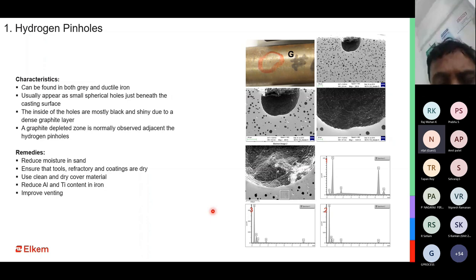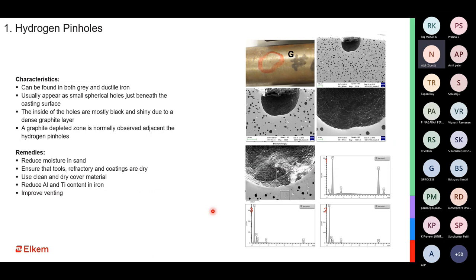The hydrogen pinhole in ductile iron is a bit different from the one in gray iron. Here also, you will find this kind of structure just below the casting surface. You can also see some graphite-depleted regions around the pinhole. Of course, it will not be a very good rim like you see in gray iron, but the region around it would have a much lower percentage of graphite nodules compared to the other part, which has a much higher density of nodules. How do you resolve it?